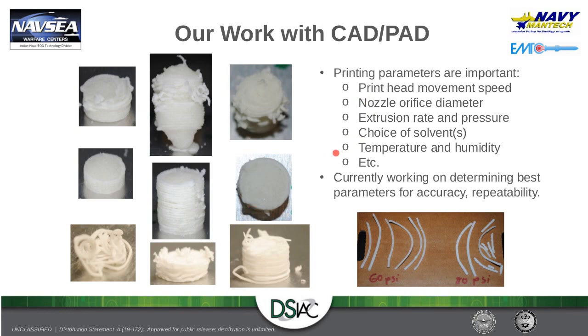The extrusion rate, or how quickly we're able to move material out, as well as the pressure, depending on how the system is set up, is also very important because it affects the rate of the material coming out and how much material is put down in a single place at a given time. Which, as I mentioned before, if put down too little or too much, you're either left with very scant beads of material or blobbing.